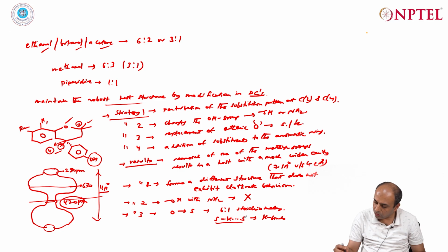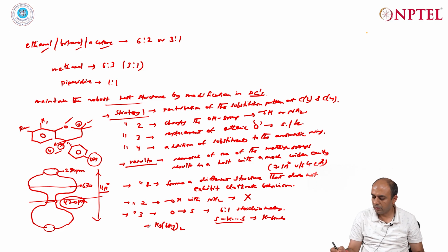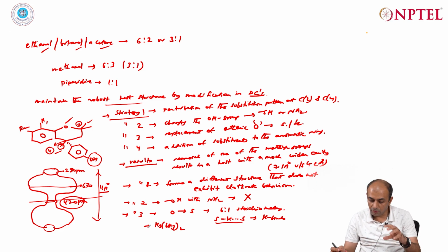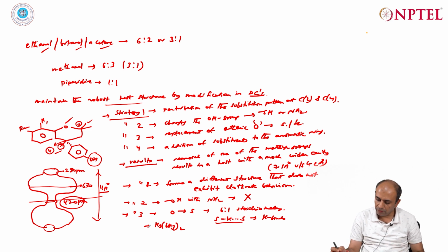and now the sulfur analog is very efficient in trapping dimethyl mercury, because this is a very toxic compound. So, this particular host, which is the sulfur analog of it, can be utilized to efficiently trap dimethyl mercury, and the resulting complex can be stored under high vacuum for several days. Only under high vacuum is it stabilized.